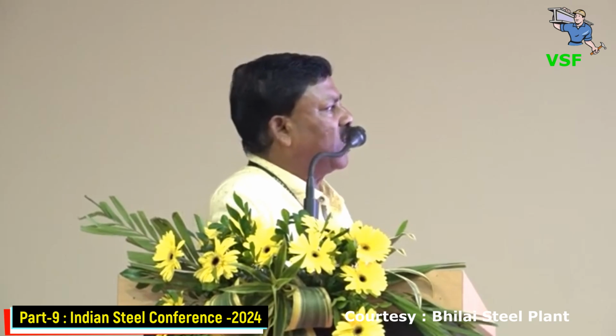We have done the slag corrosion test. Basically, we take the defined composition, collect the slag from the steel plant, and then do the slag corrosion test. Less erosion means better quality compared to maximum erosion. We have done it at 1623, and the conclusion is that higher MgO and higher crystal size give the best result.